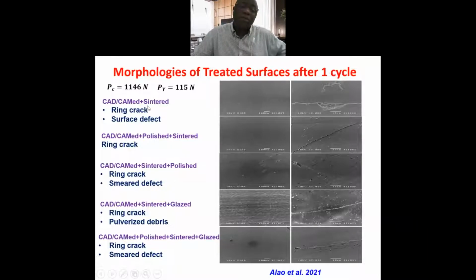So you can see for the CAD-CAM sintered, it has got ring crack and surface defect. For the CAD-CAM polished sintered process, you have only the ring crack. For the CAD-CAM sintered polished, you have also the ring crack and the smeared defect. For the CAD-CAM sintered glazed, you have the ring crack, and then because of the formation of debris, you can see the pulverized debris. For the CAD-CAM polished sintered glaze, you have the ring crack and the smeared defect.